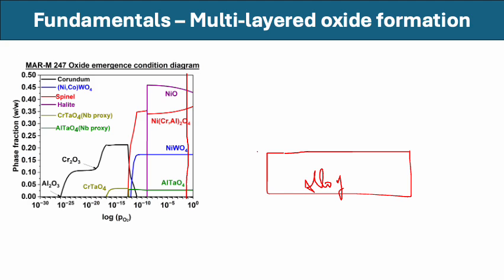But apparently the red oxide, even though the driving force for this is lower than the nickel oxide in this case, because the fraction can tell us the driving force for formation. So if there is zero fraction, then there is no driving force. If you have a maximum fraction of this particular oxide, then you have the maximum driving force for it.